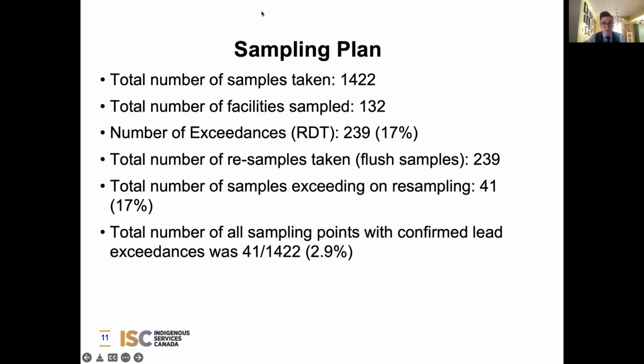And then we resampled all the sites. So there you see 239 came back with initial exceedances. All of those were resampled, and an additional 41 came back with lead in the follow-up sampling. Total number of all sampling points with confirmed lead exceedances was about 3%, or 41 sites out of the 1,422 that were selected based on the surveys and the assessments done by the EHOs.